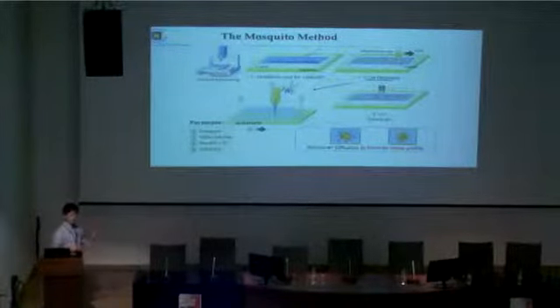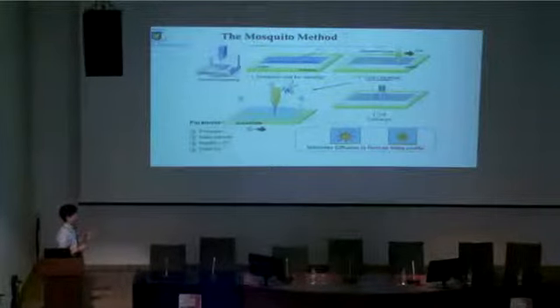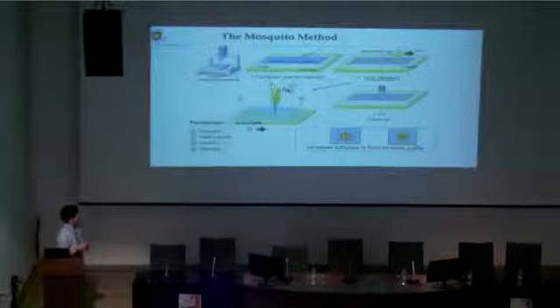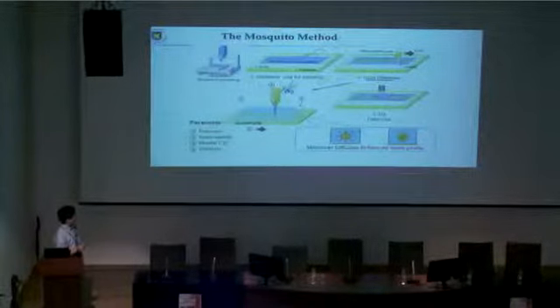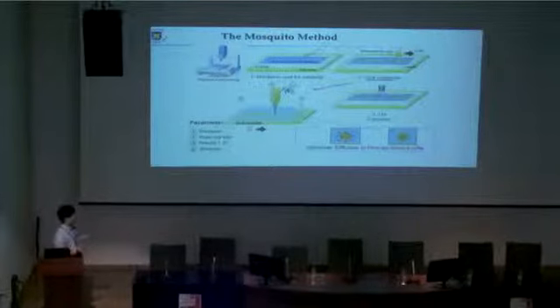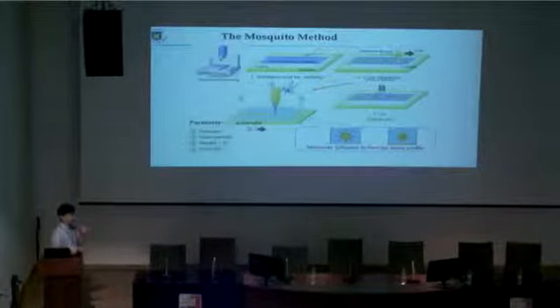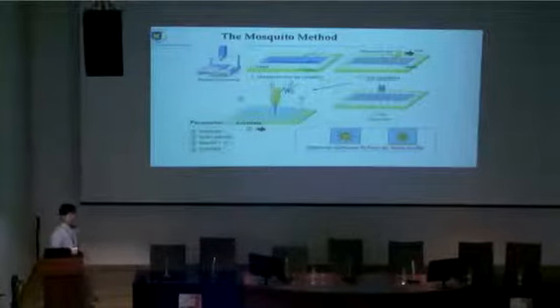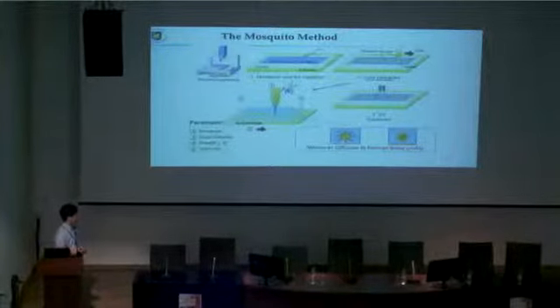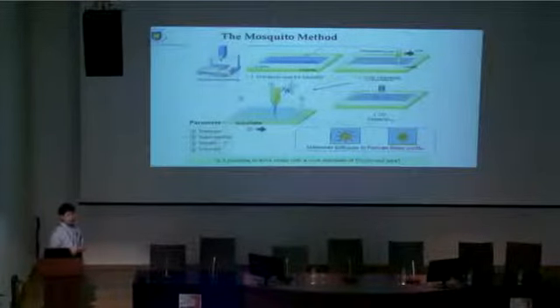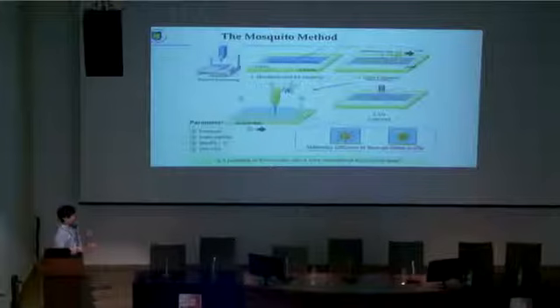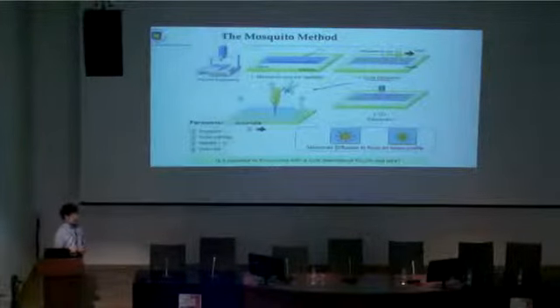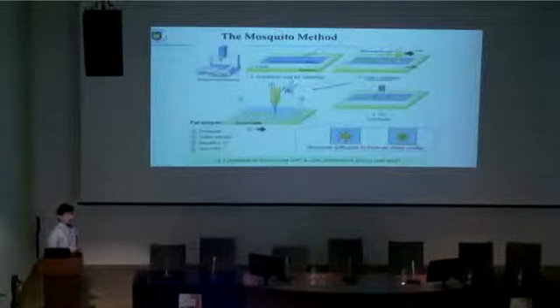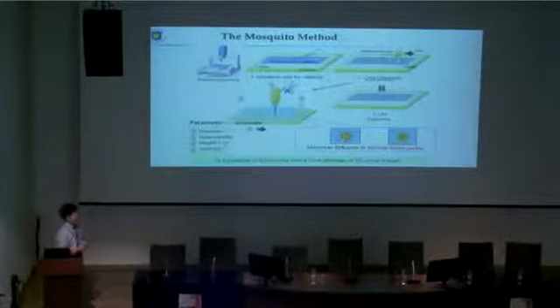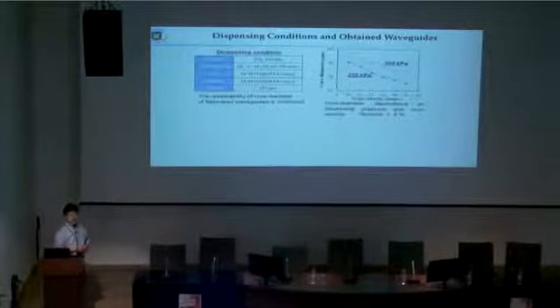Therefore, for making the graded index core polymer waveguide, we are paying attention to these 4 parameters. One is dispensing pressure. The second one is scan velocity. Of course, the needle inner diameter is very important to obtain a thin core size. And viscosity is another very important issue. So we were wondering how we can obtain such a thin core, like 50 micron, from a needle, because the core monomer has high viscosity. However, it is very easy.